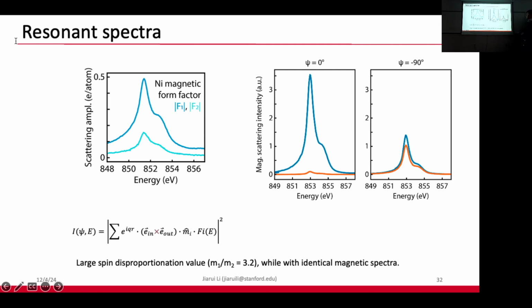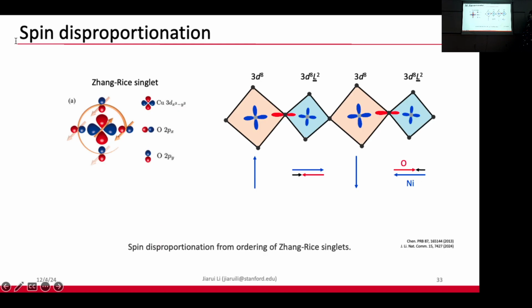And then they show a highly similar spectral shape despite this common factor. And this is really puzzling to us: if we assume that nickel 1 has a magnetic moment of 1, so it is a spin 1 system, then nickel 2 should be 1/3, which is close to a spin 1/2 system. And we know that in these atomic configurations, a spin 1 system and a spin 1/2 system should behave very differently in their electronic configurations, so it's very unlikely for them to have a highly similar electronic spectrum. So how do we resolve it?